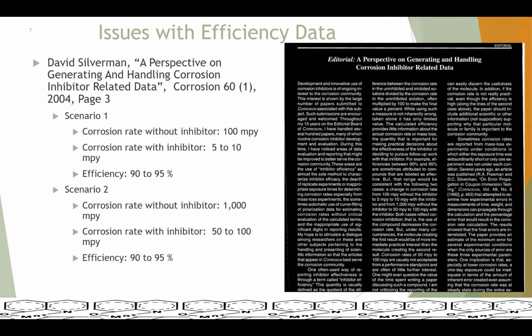And we would like to bring two aspects of it. Again, this is directly from Dave's paper. In scenario 1, a laboratory reported a corrosion rate in the absence of corrosion inhibitor to be 100 mpy, and in the presence of corrosion inhibitor, anywhere between 5 to 10 mpy. This is the data, but what they report is efficiency, inhibitor efficiency 90 to 95%.